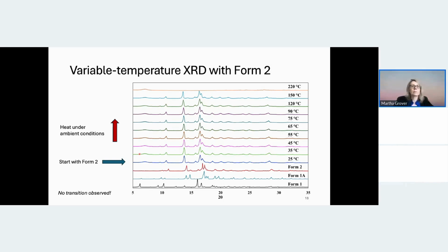So here we start with Form 2, and this is heated under ambient condition, and we heat all the way up to 150, and we don't see any change. So we see the same structure. So we conclude that we do have a physically stable form all the way up until melting.